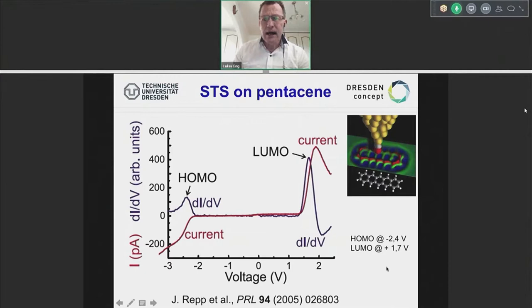Actually, the HOMO level is at -2.4 volts down here, the LUMO at +1.7. So a band gap, typically, which is as big as 4 electron volts. So again, math-wise, you do the derivative, the dI/dV of this measured curve, and you can actually see the maximum of this HOMO, the maximum of this LUMO. And the rest is basically the band gap, the electronic band gap, I have to say.